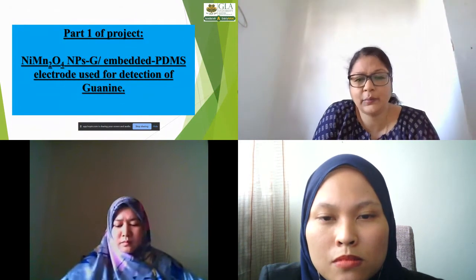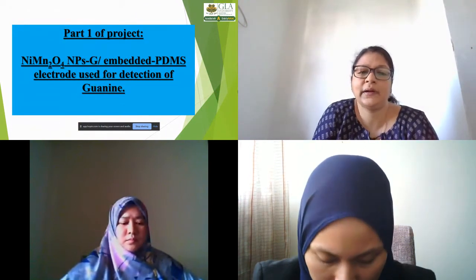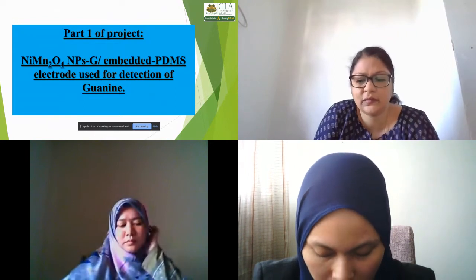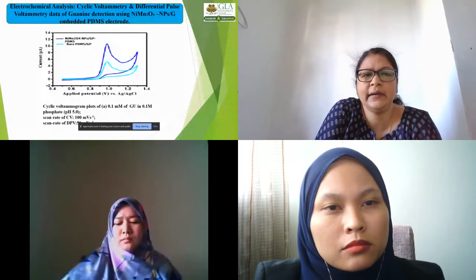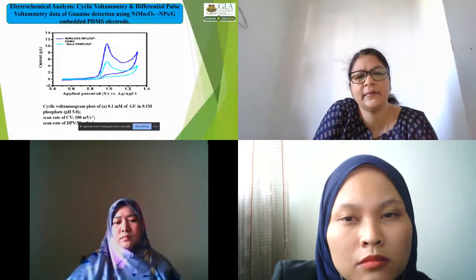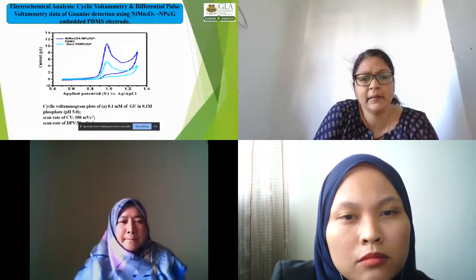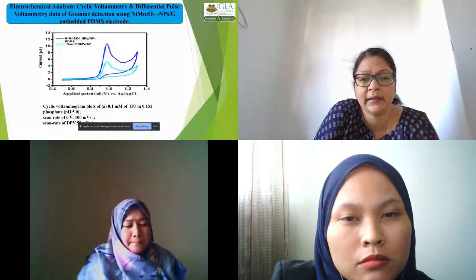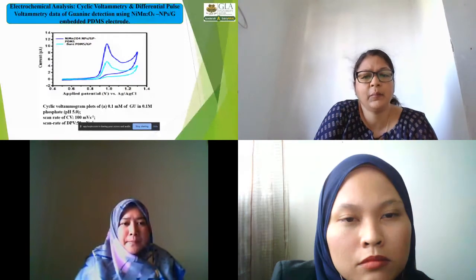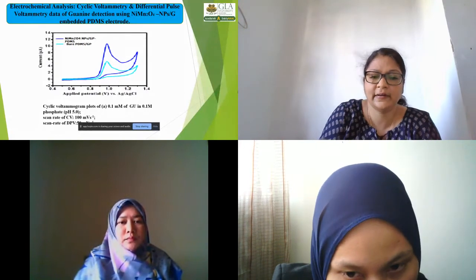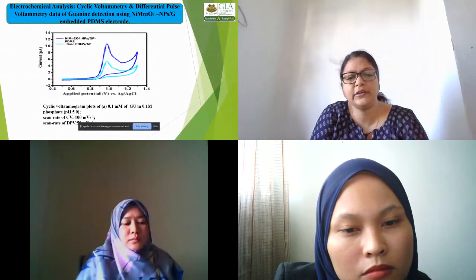Now, in part one of our project, we used a nickel manganate nanoparticle graphene embedded PDMS electrode for the detection of guanine. After that we did electrochemical analysis. Cyclic voltammetry and differential pulse voltammetry were the standard methods used in the presence of 0.1 millimolar guanine and in phosphate buffer saline of pH 5 at 0.1 molar. The scan rate that we found was 100 millivolts per second for cyclic voltammetry, and for differential pulse voltammetry we got 50 millivolts per second.